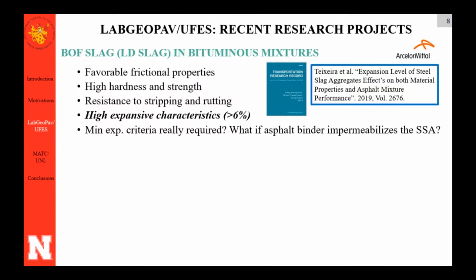They don't say that we cannot use slag, the Brazilian standards, but they say, okay, if you want to use it, you have to cure this material before you use it. Basically, put it in water and make the material expand before it's used, and it has to have a maximum level of expansion of 3%. But we start to think, is this 3% requirement for maximum expansion really required for use on an HMA layer in the asphalt?